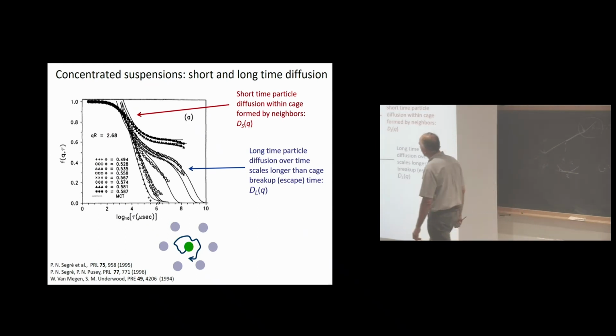The data are, of course, from Pusey's group at the time. So that's the intermediate scattering function, okay? And this is hard spheres, experimental hard spheres. I increase the volume fraction. You see I have one relaxation process. And as the volume fraction increases, I have the evolution of the second process, and eventually pretty much no relaxation,